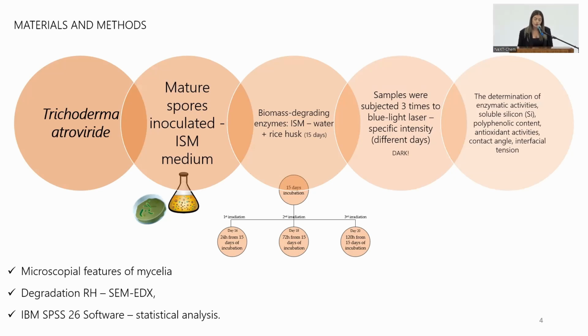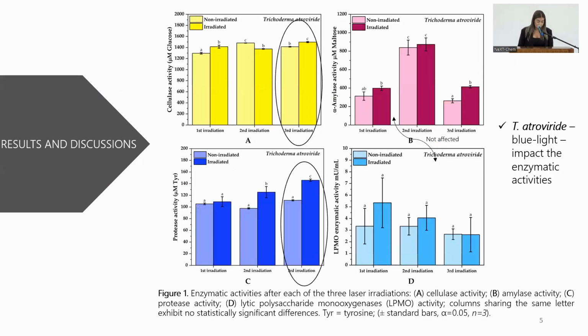The supernatant was used to assess the enzymatic activities, the soluble silicon, the polyphenolic content, and antioxidant activities; interfacial tensions and contact angles were measured as well. Moreover, microscopical features of mycelia were evaluated. The degradation of rice husk was visualized by SEM, and SPSS software was used for statistical analysis. Exposure of Trichoderma atroviride to blue light was observed to impact the enzymatic activities. The highest cellulase and protease activities were observed after the 3rd irradiation and were higher than in the non-irradiated samples. The amylase and LPMO activities were not significantly affected by blue light.